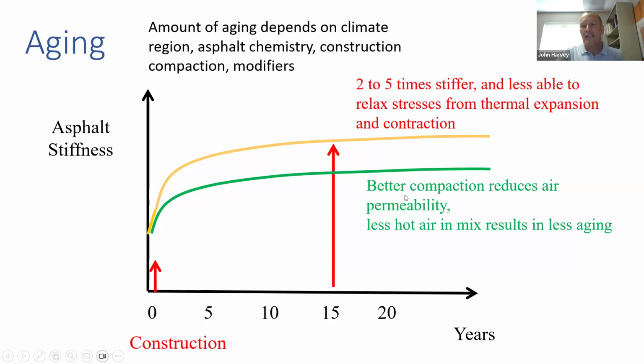If we have good asphalt compaction, good compaction makes it so that the surface is less air permeable, and good asphalt compaction is going to help slow down that aging and potentially cap off the maximum aging that occurs, because if the hot air can't get into the mix, the hot air can't cause aging.